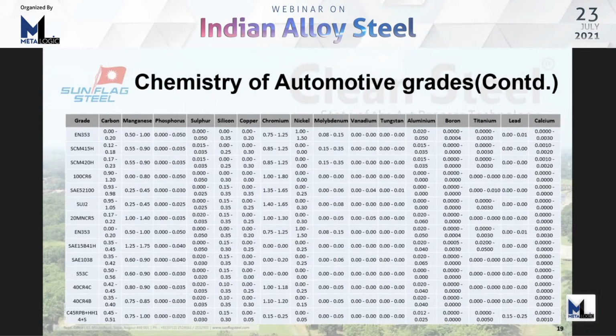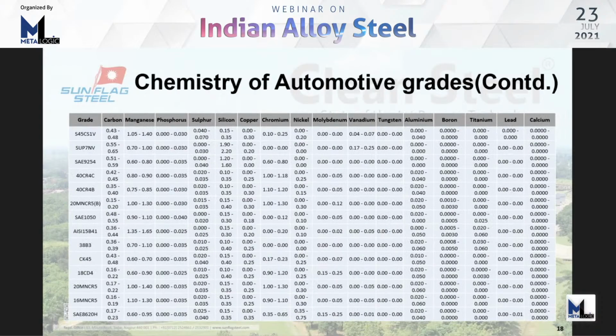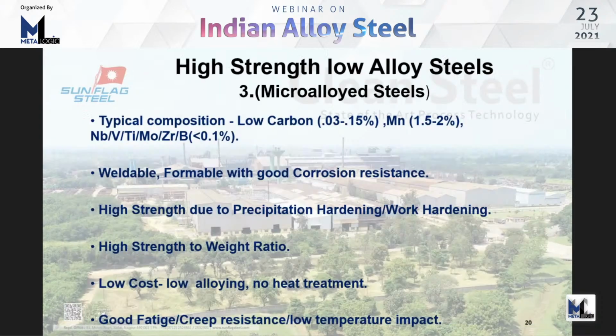Now these are the chemistries of the grades which I have indicated earlier with parts. Now we come to high strength low alloy steels, which are also called HSLA steels, normally having low carbon, manganese between 1.5 and 2%, and less than 0.1% of elements like niobium, vanadium, titanium, moly, zirconium, or boron. They are weldable, formable, they have high strength, they have high strength to weight ratio, and cost is very low because of low alloying and no heat treatment. It has got good fatigue properties, creep resistance, and low temperature impact.